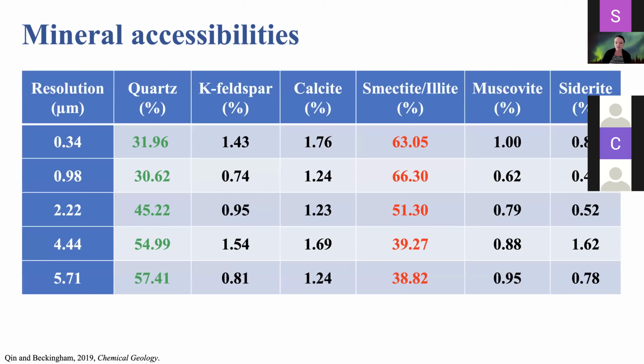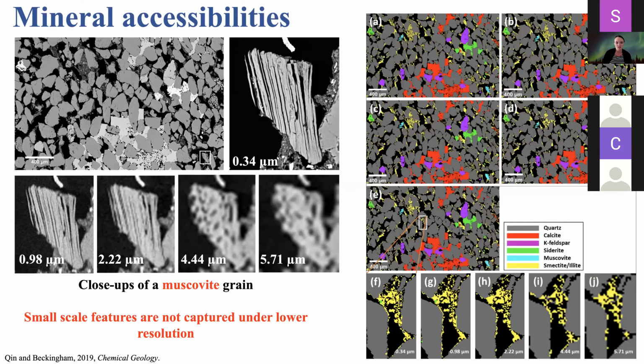And what we noticed is that with decreasing resolution, we had a decrease in the accessibility of smectite and an increase in the accessibility of quartz. And oftentimes the smectite is present as a coating on the quartz mineral surfaces, for example. And if we take a look, just to give you some examples here, we have some close-ups of these small scale features that are really challenging to capture with lower image resolution.